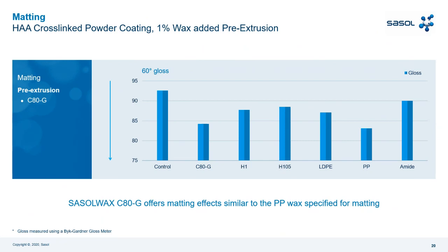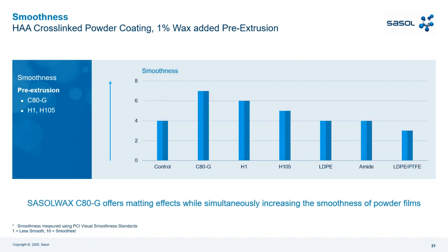Then of course follow all the other Sasol wax, and amide wax give a quite high value, and of course H1 follow. Then we see the smoothness. Smoothness again in pre-extrusion. You see the control that has a low value. We need to check the highest value. Sasol wax C80G. So again, for someone that joined only now, it is the micronized version of Fischer-Tropsch wax with C80 with 80 melting. We have Sasol wax C80G that gives us the best value as a smoothness, and then respect Sasol, all the Sasol wax, and respect also the LDPE, the amide, and the LDPE PTFE.